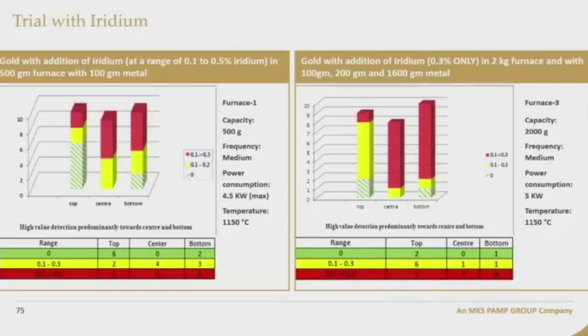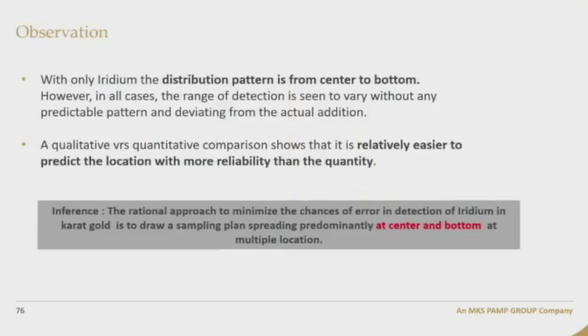The green portion indicates that we couldn't detect iridium, or we detected less than 0.1%. The yellow shows 0.1 to 0.3%, and the red shows a high presence of iridium. So these 2 slides clearly say that there is a tendency of iridium to be found more at the center and at the bottom. So what do we conclude? With only iridium, the distribution pattern is from center to bottom.